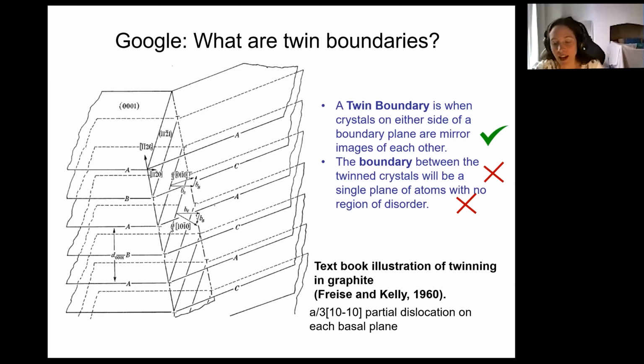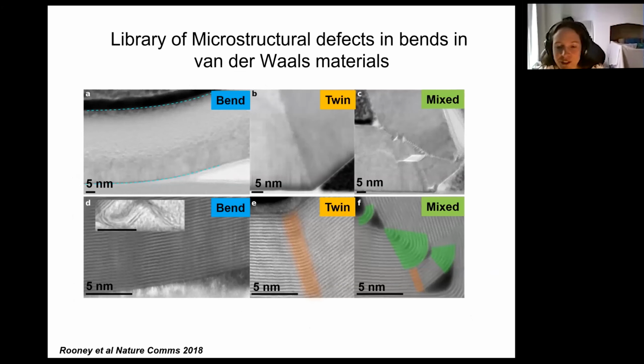So hopefully we've shown that we actually need to reconsider what's written in these textbooks, and there is not an abrupt boundary for graphite. We have a twin type boundary, but this is delocalized, and the delocalization is of the order of a few nanometers. Okay, so we didn't just see twins when we looked at deformed microstructures.